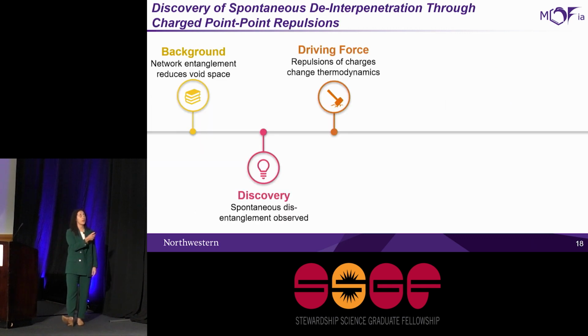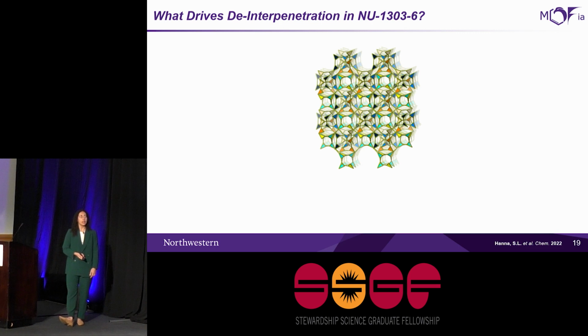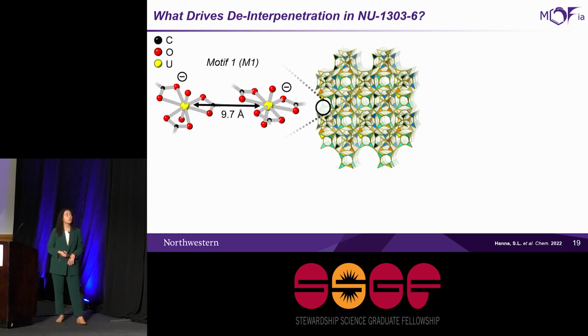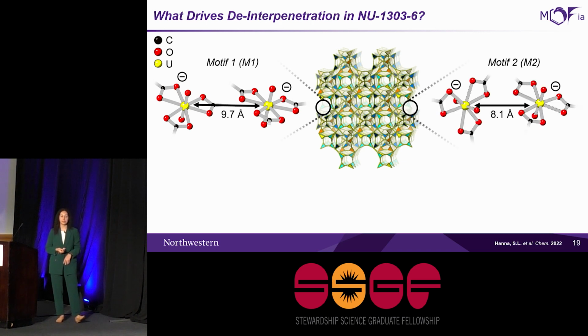So I wanted to understand what the driving force for this process was. And you can understand the driving force by going a little bit more deeply into the structure. So throughout the structure, there are these 2 different motifs that repeat, where you have these uranium nodes, each of which have a -1 charge on them, and they're separated. So these are nodes on different lattices throughout the structure, and they're separated by a pretty short distance, 9.7 and 8.1 angstroms. And so these reminded me a lot of like 2 North Pole magnets. If you put 2 North Poles together, they're going to automatically want to repel each other and go further and further from each other.